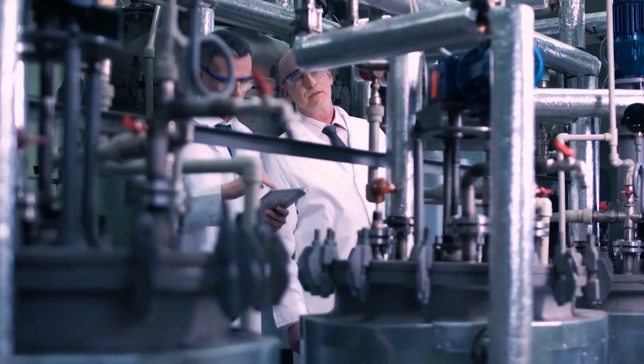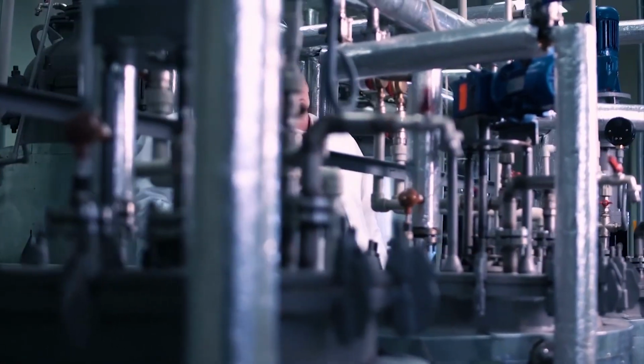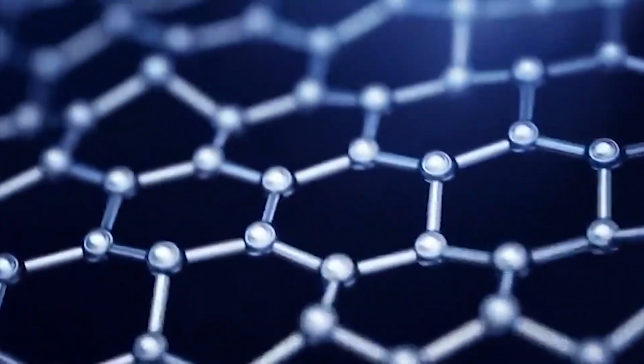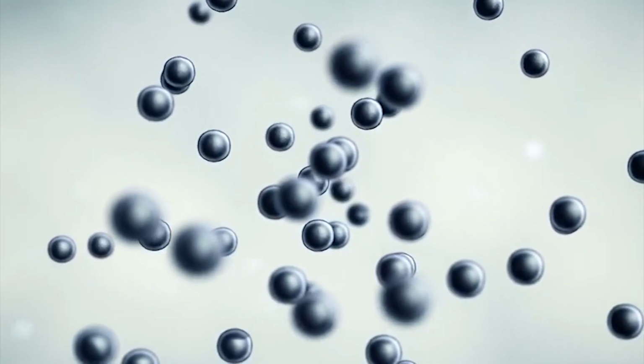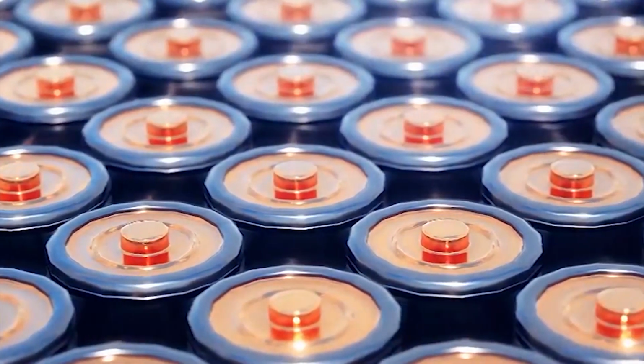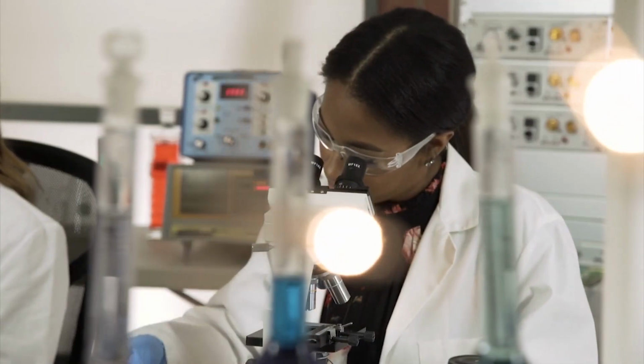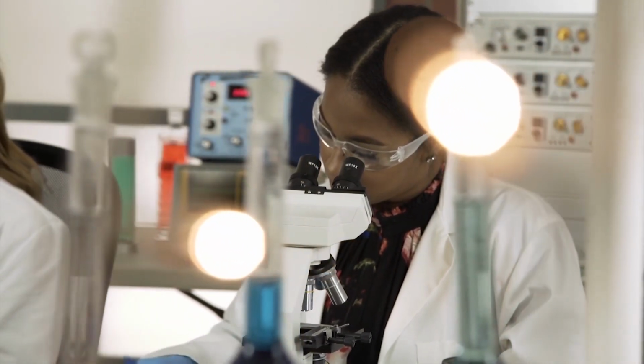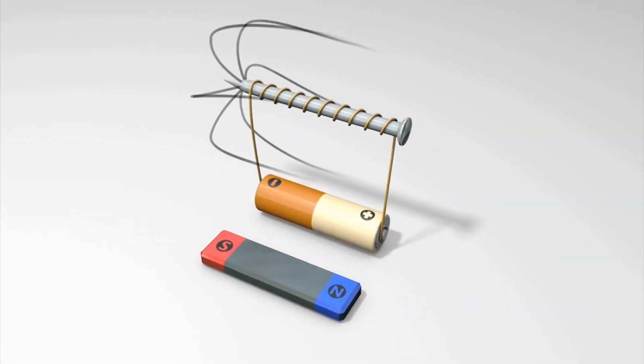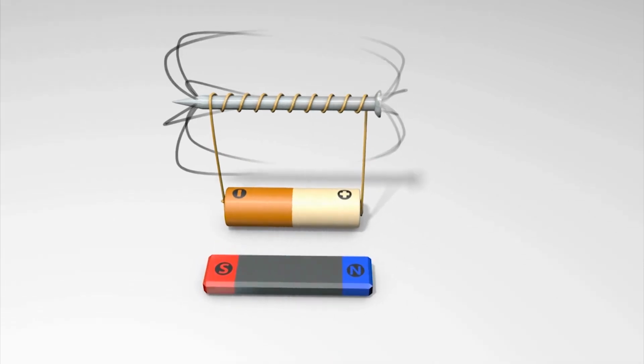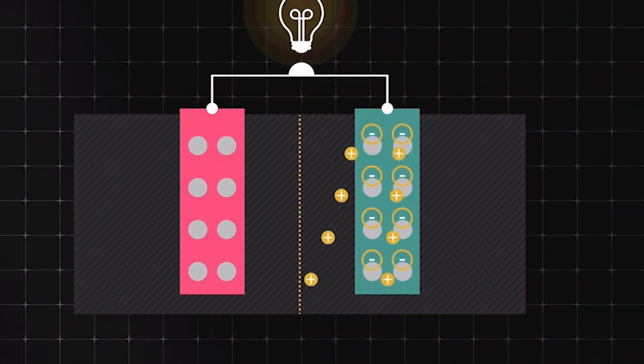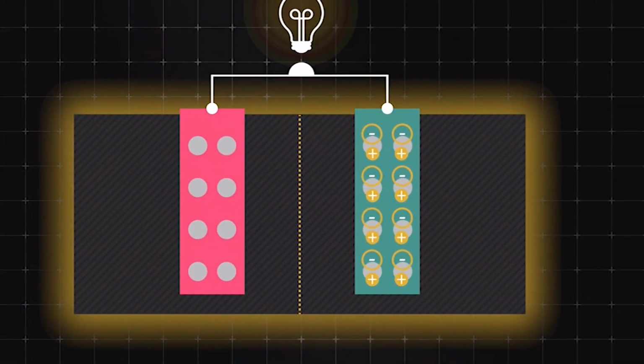Scientists are currently experimenting with alternative forms of electrolyte, like a ceramic-based electrolyte or a hybrid gel-like electrolyte, to reduce the shuttle effect within the batteries. Early this year, a research team announced the use of a sugar-based additive that effectively inhibits the release of polysulfide chains from the cathode within the battery. A successful prototype was able to achieve 1,000 charge cycles and a 700 mAh per gram capacity, which is a step in the right direction for sustainable lithium-sulfur batteries.